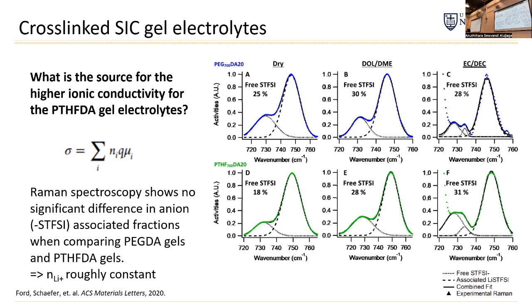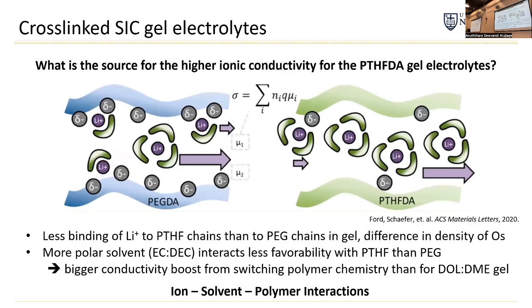And this particular anion, its local environment really changes the Raman spectrum. So if you have a cation nearby, or if it has a difference in mobility, you see a change in this band. So we were really surprised that in this case, the band is really similar all the time. So between the PEG, between the poly-THF, and with different solvent environments, the band is really similar. And so we thought that the number of lithiums that are dissociated from the anion is roughly similar in all cases. So this can't explain the difference in the conductivity.